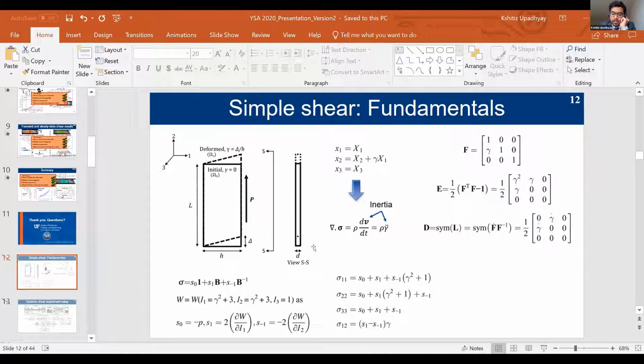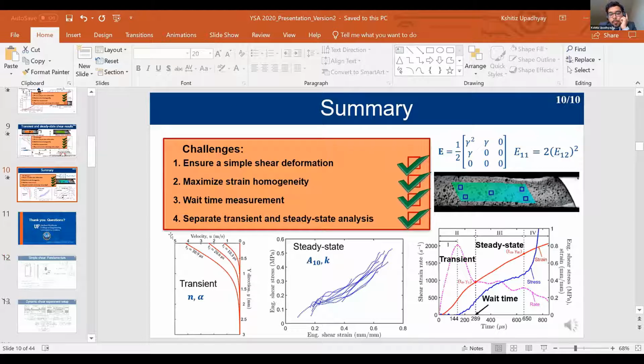In the first part of the test, in the transient state of deformation, there is a very high inertia. So I can't model that with any constitutive model that assumes no inertia effects. No, but you measure it. You measure it through your acceleration. Yeah, but I use a different model to model that response. There is a transient momentum diffusion during that stage of deformation, and I model it using this Navier-Stokes equation. So I am modeling it.